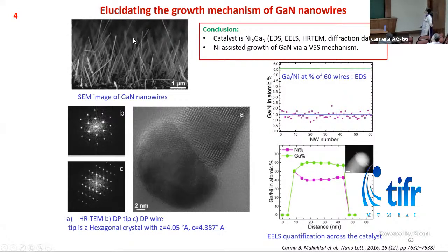Now, here is an example of gallium nitride nanowire studied using TEM. This is an SEM image of gallium nitride nanowire. Here we tried to answer the question whether this nickel-assisted growth of gallium nitride happens via VLS mode or VSS. By VLS, I mean vapor liquid solid, and by VSS, I mean vapor solid solid mechanism.